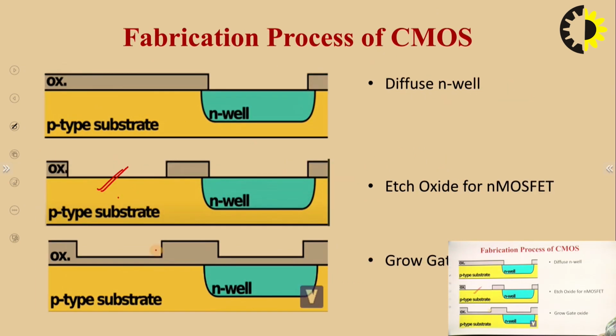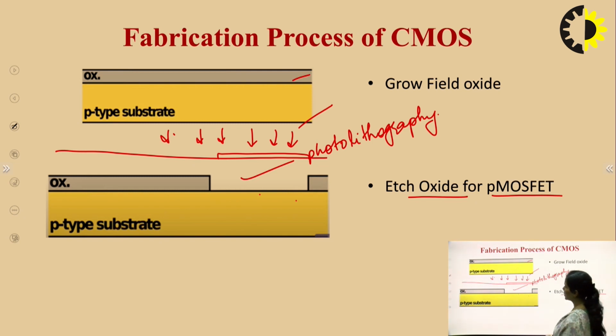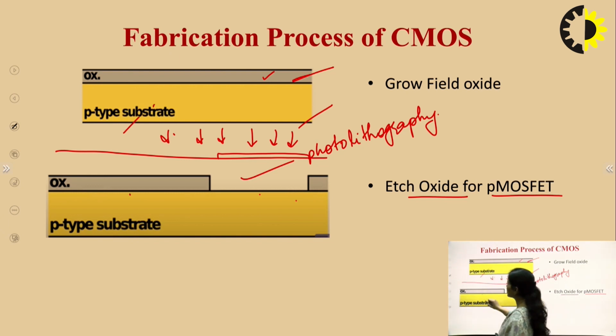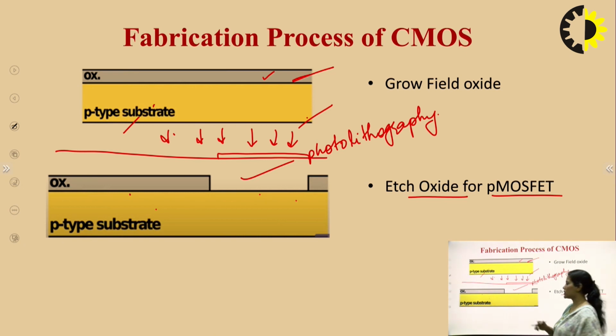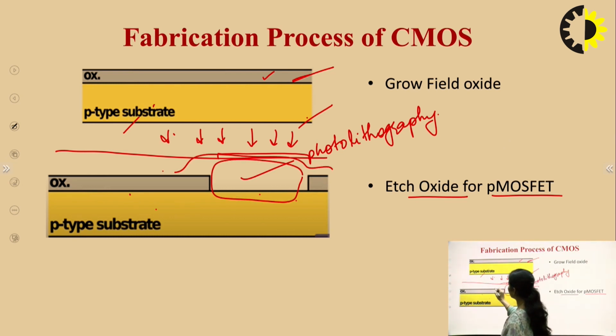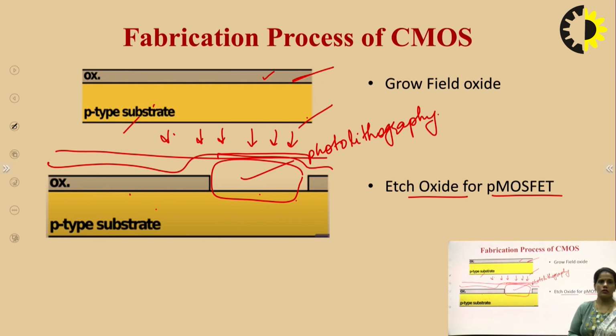So let's give a quick recap to the fabrication process of CMOS. In the fabrication process of CMOS, we are again starting with the P-type substrate. Here in this case, the CMOS is fabricated on the P-type substrate, starting with the deposition of oxide layer on the P-type substrate. And I have not shown this step between these two steps. Between these two steps, there is a process of photoresist deposition. A photoresist layer is deposited on the oxide layer, and after using the mask and patterning, the photoresist has been removed from this portion, and in the final step the photoresist which has been deposited on the surface has been removed.